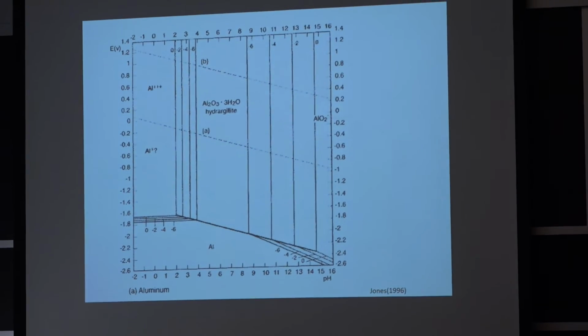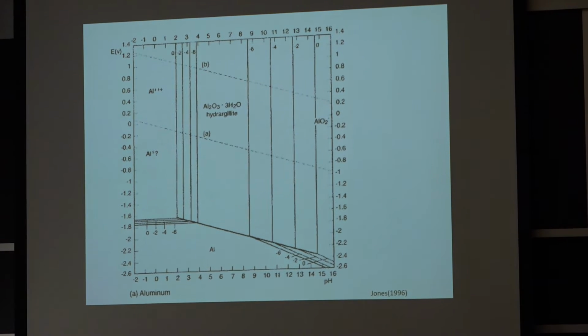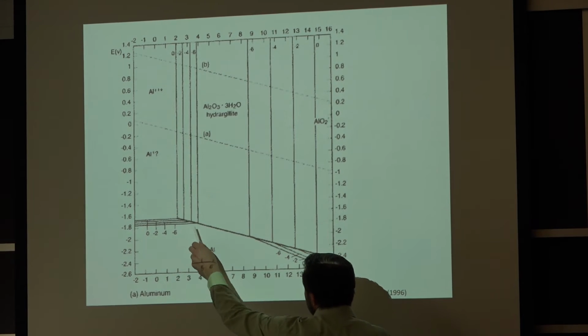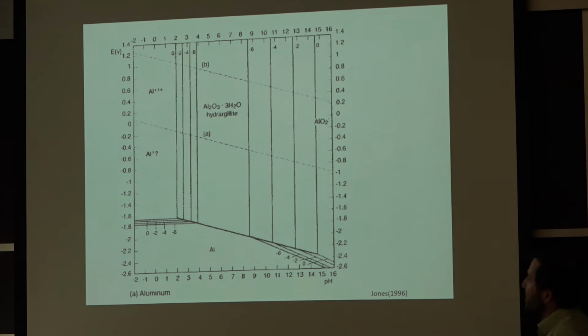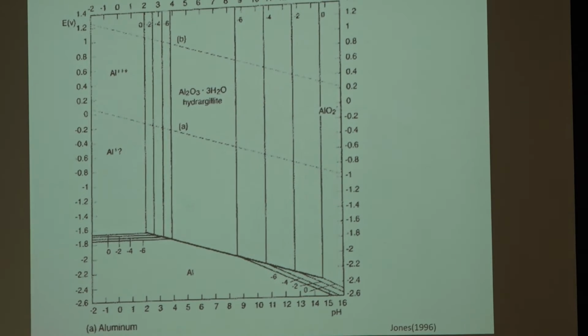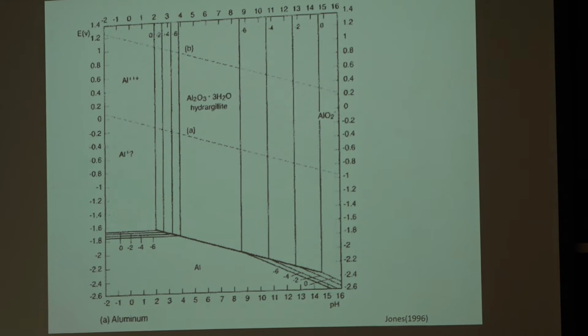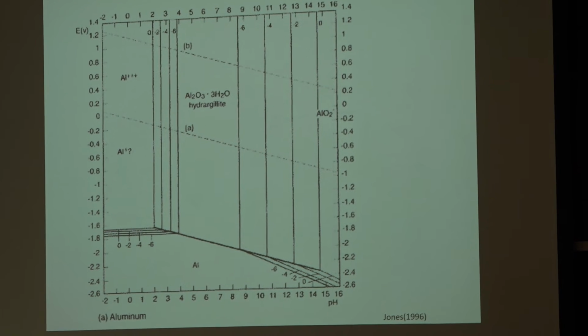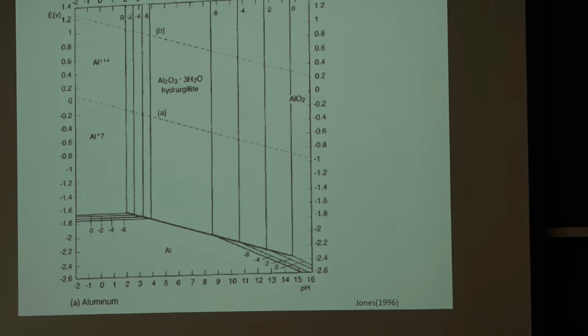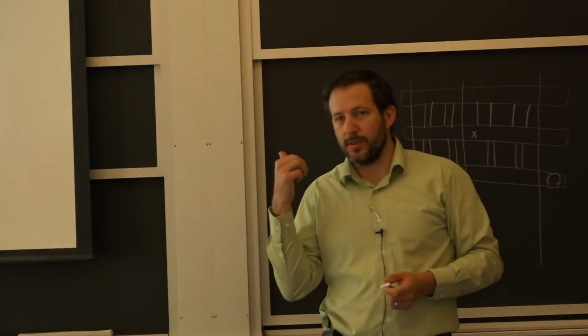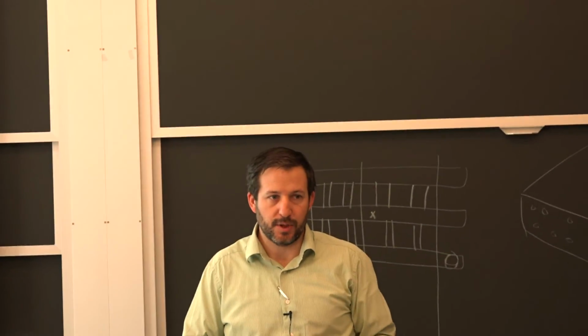With aluminum, we're blessed because in a typical atmospheric condition, you have a stable oxide on the surface. So that is from pH approximately 3 to 9, you have this oxide forming that is relatively stable. Now, we have to take that into account, because pH 3 to 9 doesn't cover all the applications. If you use an acid cleaner for a piece of aluminum, then you can get into trouble because you lose that protective oxide.